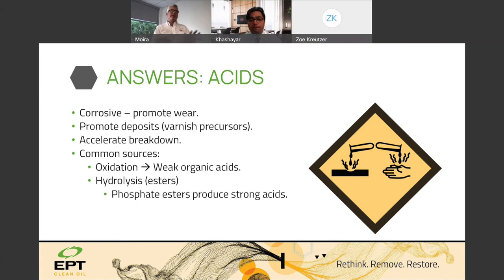Acids, though, should be very stable in your lubricants. If you had an acid number of 0.05, 0.06 as a new fluid, you want to see a very, very gradual increase in that acid number over its life. If you see a large spike in acid number, that would be a very bad indication that something serious is happening. Typically, the base oils, especially the group 2 and beyond oils, are very, very stable, and you'd not expect to see sharp acid changes. So that would be one of those variables you just want to see nice and steady.